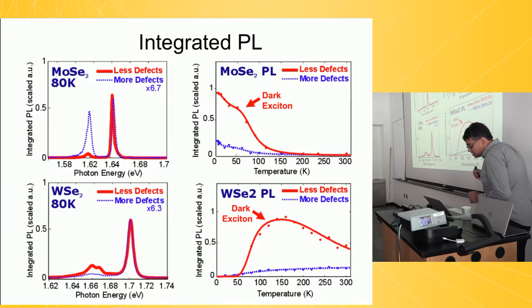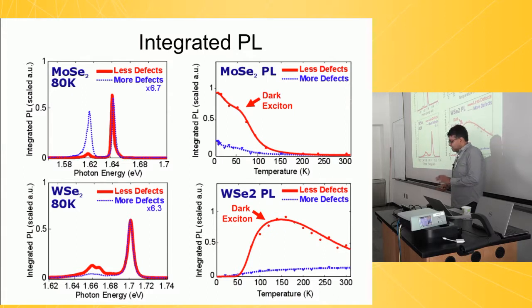I did not mention here, I don't know why it's not here. If you look at the absolute magnitude of the photoluminescence, we also find that it is roughly inversely proportional to the defect concentration that you have. So if you have a material that has 100 times less defects than another material, we get 100 times more light out of it. And you can sort of see this here. These are two crystals that are both not very bad, but you can see that the cleaner crystal just has a lot more light than the crystal that's not as clean.